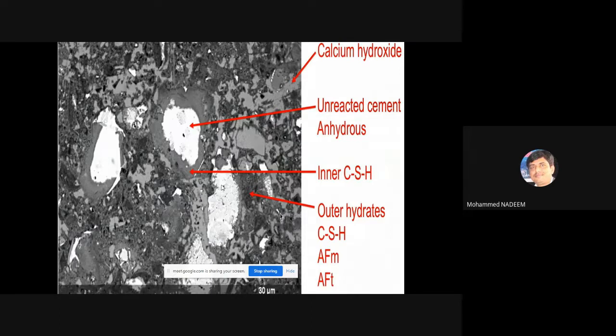If you see your concrete through the electron microscope, it looks like this. You have calcium hydroxide, which looks like this. These are unreacted cement particles, because water has not touched these cement particles, so they are unreacted. This is the inner CSH gel created because of tricalcium silicate and dicalcium silicate, and there are other hydrates. So this is the actual picture of a concrete through the electron microscope.